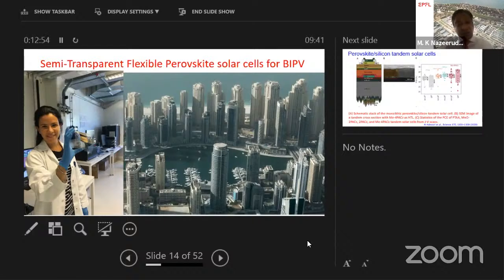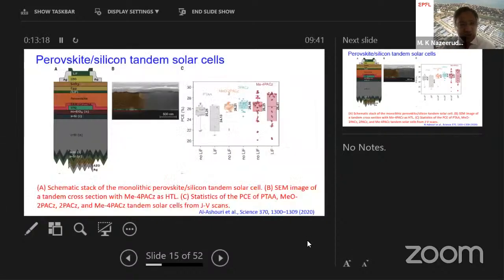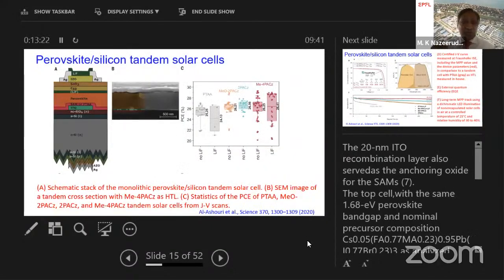Now there are several companies working on silicon solar cells. They want to adapt these perovskite materials on top of silicon solar cells for tandem configuration applications, because we have reached the limits of silicon solar cell efficiency, the thermodynamic limits. So we cannot increase the silicon solar cell efficiency beyond what we have today. So one approach, the next slide shows you the possible approach to increasing the power conversion efficiency of silicon solar cells by combining perovskites on top of silicon solar cells. This publication came very recently. Al-Ashuri, a student who worked in the Berlin group, published this work.